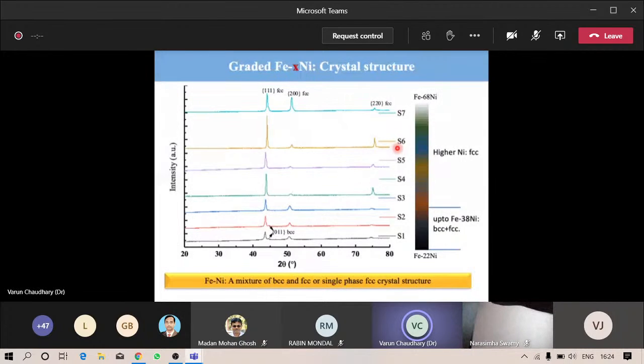So this is one sample. On one side, it has iron 22 nickel, and on the other side, iron 68 nickel. As you can see here, for the higher nickel side, we have a pure face-centered cubic structure, but at the lower nickel side, we have a mixed phase. The second phase of BCC can be seen by this second peak here.